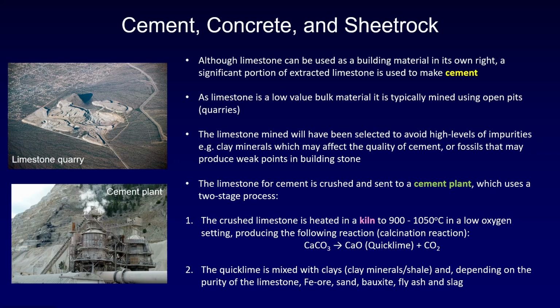So the limestone will be mined, and you will try and select the best quality limestone you can, because you're going to want to avoid high levels of impurity. So you don't want too many clay minerals in your limestone because that's going to produce a slightly lower quality cement. You're also going to be trying to avoid things like layers of limestone which are very, very rich in fossils.